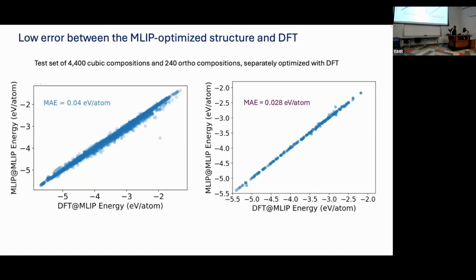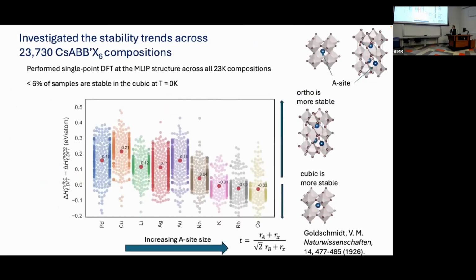It's also the case that we did two different tasks. One is to these cubic structures, and we also applied it to a smaller set of these tilted orthorhombic structures I mentioned that are important in this material class. You can see in this case it performs a little bit better, but that's probably just based on it being a smaller compositional space. But nonetheless, these for us were looking very, very good. And then once we have a cheap potential, we could start to ask very complicated questions from the data set, which would have been impossible a few years ago with just DFT.